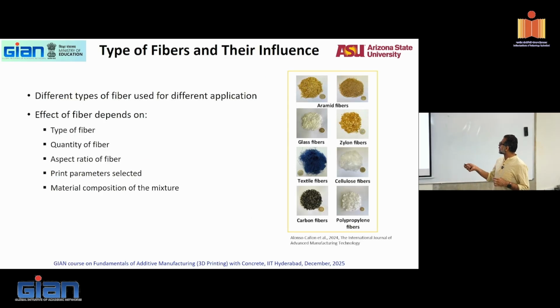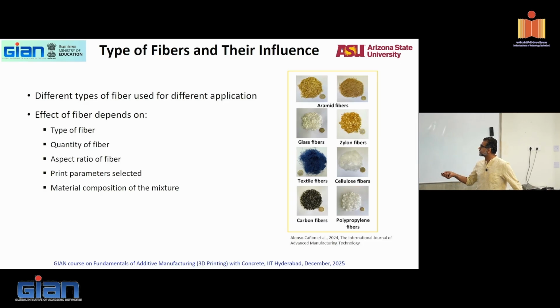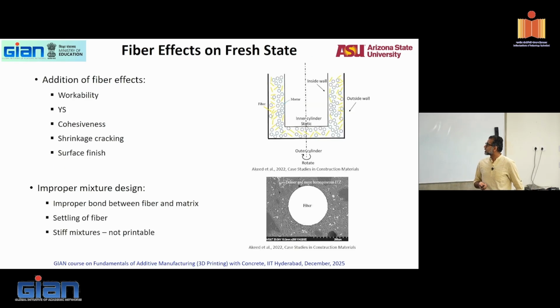Types of fibers, you have lots of different types of fibers that you can use: aramid, glass, textile, cellulose, polypropylene, lots of different fibers. The effect depends on the type of fiber, quantity of fiber, aspect ratio, which is length to the least lateral dimension of the fiber, print parameters selected: how quickly you're printing, how many layers you're printing up, all of that. And then the material composition. So again, fibers, we'll see more of that when we talk about mechanical properties, but fibers also influence the properties.